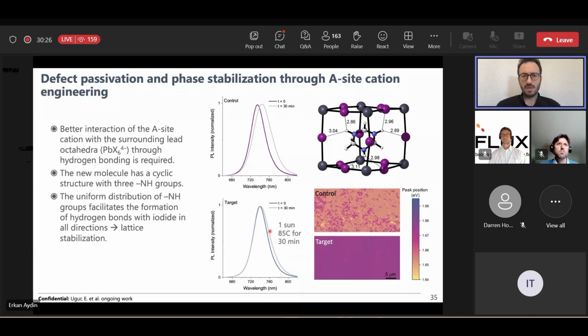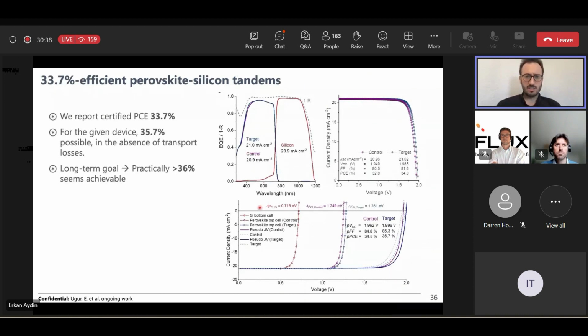For instance, you see here the PL peak position from the perovskite layer after 30 minutes at 1 sun and 85 C. So basically, it's also helping for the phase stability. This device, last year in May, almost 1 year ago, led to another record efficiency of 33.7%. And with this device, again, we repeated the same measurement, and we found that these devices have potential close to 36%. But in the long term, we predict these perovskite-silicon tandem cells can go above 37%. That is pretty much possible if we can further minimize the losses.